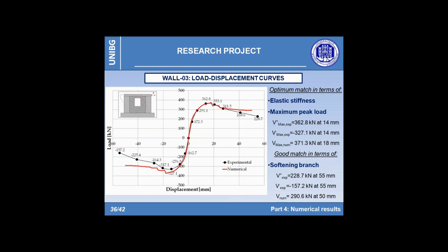Finally, the last comparison in terms of load displacement curve is presented, concerning wall 3. The numerical predictions are in substantial agreement with the experimental evidence, both in terms of initial stiffness and peak load. The maximum force obtained for 0.65% drift is equal to 371 kN, respectively 2.3% and 14.5% higher than the experimental values, registered as usual at 0.5% drift.